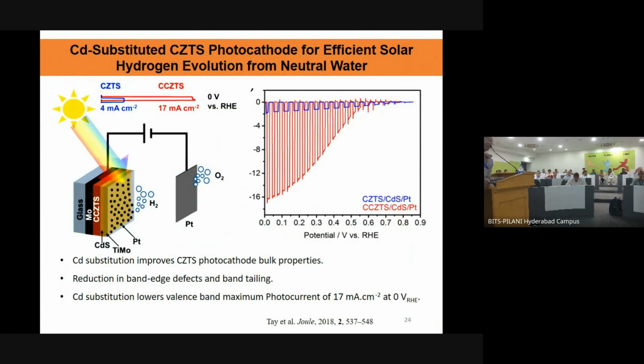But if you scan the literature, as I mentioned, most of the reports were basically on a working electrode. Significant improvements were reported when a p-type combination like CZTS was loaded with platinum. So this is the Cd substitution, reported in the literature. If you look at cadmium substitution, it significantly improves the activity of the photocathode.